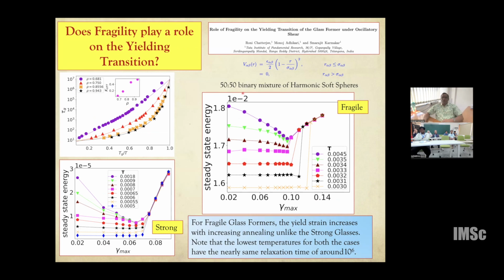This is a 50-50 binary mixture of harmonic spheres. At a density of, for example, 0.681, you get a state which is more strong-like, and you can take this state and cool it to go to a zero-temperature glass and look at its dynamical properties. But if you take a density of 0.943, which is these black stars, then you get a very fragile liquid, and you can quench this liquid to get a glass generated from these fragile liquids. So we repeated this same oscillatory shear in these samples.